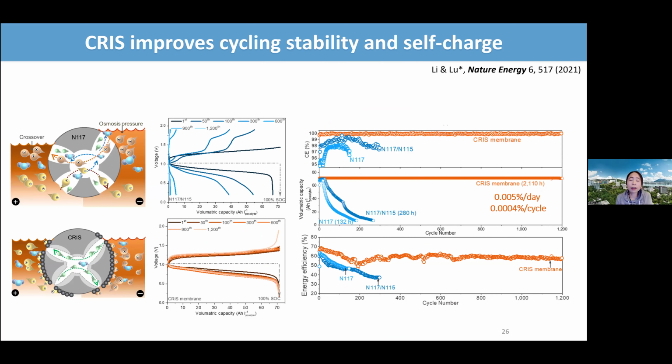So while this is a very, I would say, simple idea, it is actually surprisingly effective. So you can see the polysulfide flow battery using Nafion membrane, from 1 to maybe 50 cycles, you almost decay more than half, and after 300 cycles, all the capacity is mostly gone. And this is exactly the issue that all the previous polysulfide flow batteries are facing.